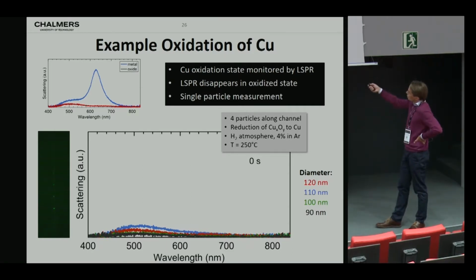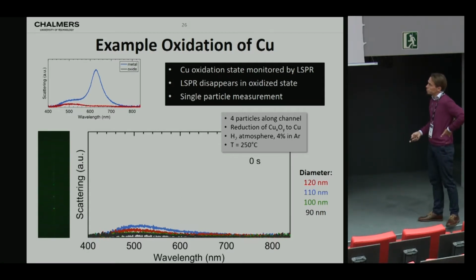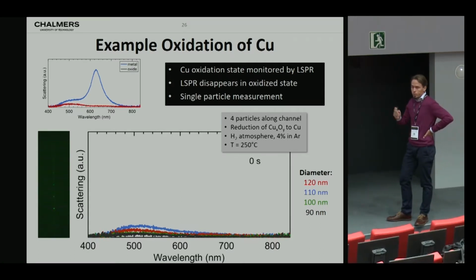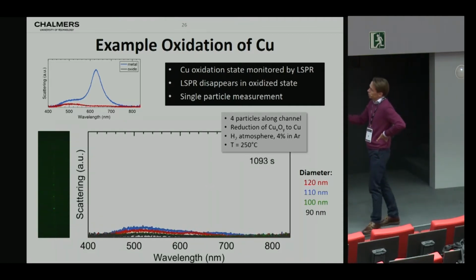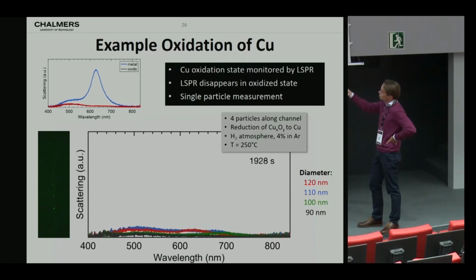We have these 4 nanoparticles in the channel with slightly different sizes. We start with them being in the oxidized state, and we apply 4% hydrogen and argon at 250 degrees to follow in real time how they are reduced back to the metallic state. And this is a video of the spectral response as a function of time here.